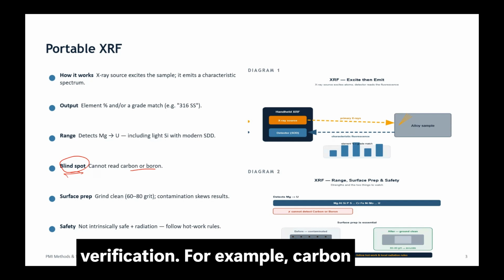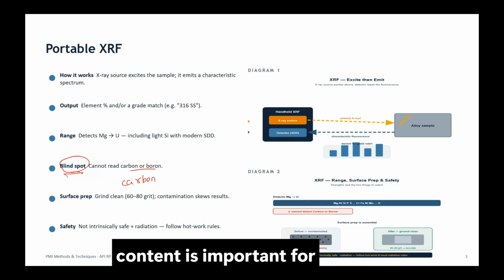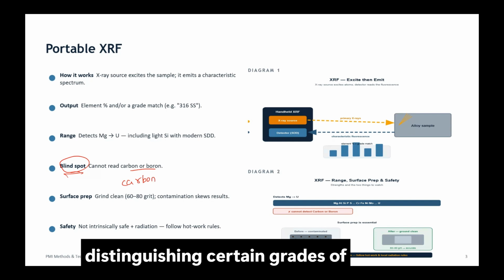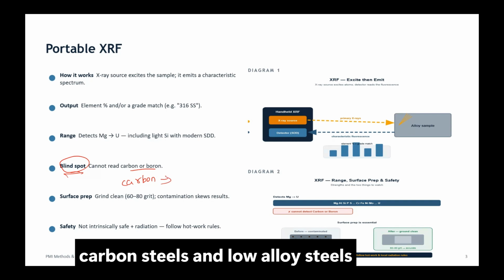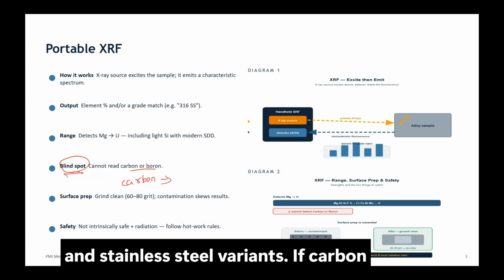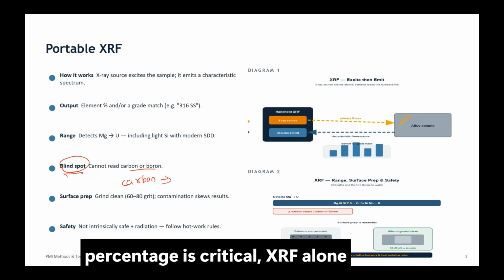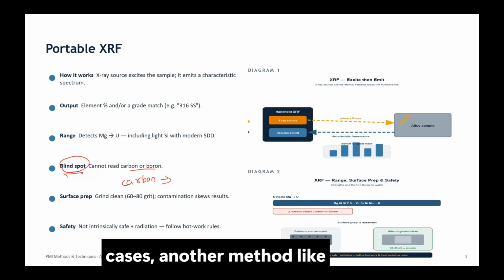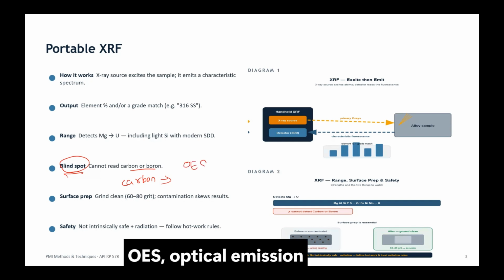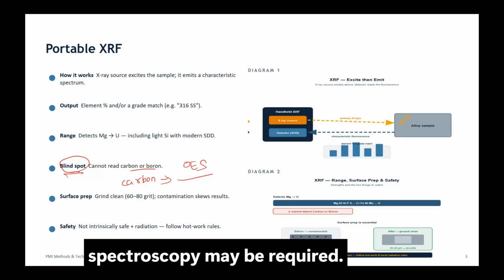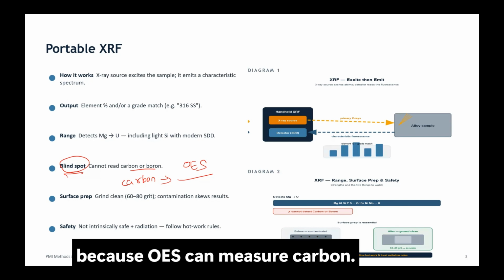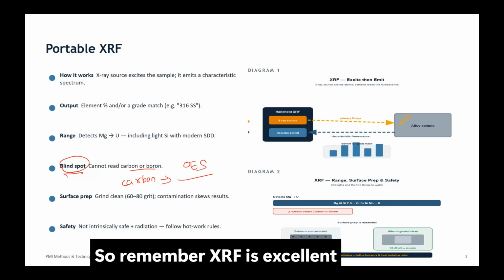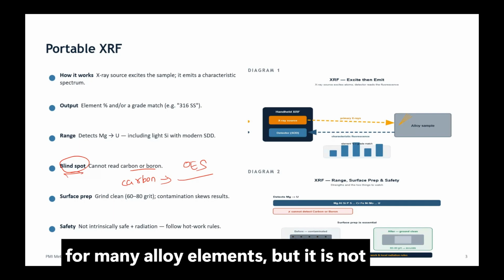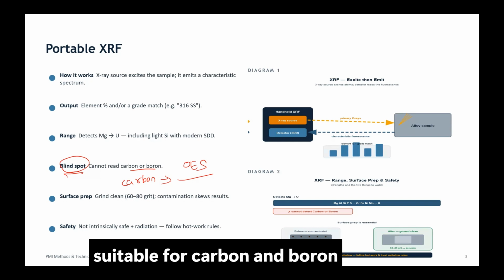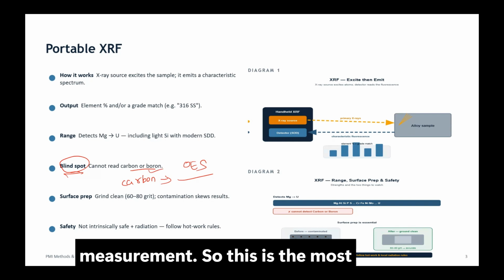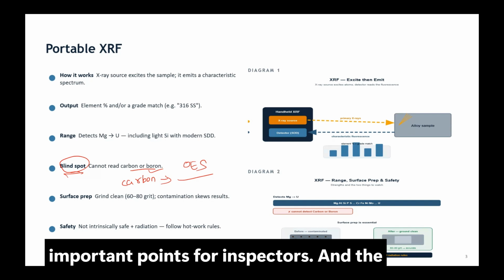For example, carbon content is important for distinguishing certain grades of carbon steels, low alloy steels, and stainless steel variants. If carbon percentage is critical, XRF alone may not be enough. In that case, another method like OES, optical emission spectroscopy, may be required because OES can measure carbon. So remember, XRF is excellent for many alloy elements, but it is not suitable for carbon and boron measurement. This is the most important point for inspectors.